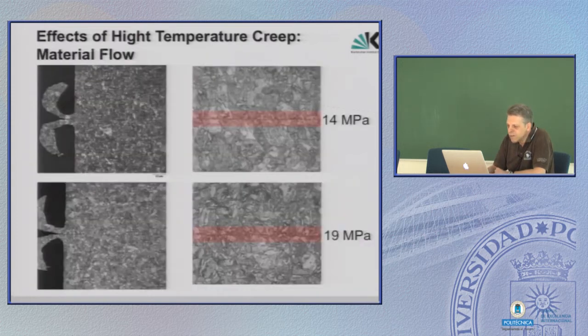Also another funny side effect was that since the blades are not perfectly straight, and you have seen there is some roughness in it, due to the pressure on these blades and due to creep and diffusion, there is a material flow outside of the end of the channel, which produces, not so big, a few tenths of a millimeter, but still, internally in the cooling channel you have long, strange features along the weld line. That's a side effect which we didn't know before.